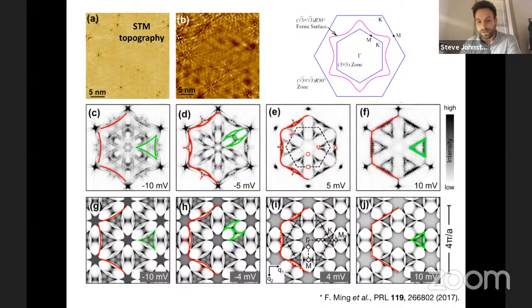And then you cross the Fermi energy at the unoccupied side, it pulls in even more. And when you go well above the Fermi energy, it almost flattens out and disperses even further in. So this is sort of the first empirical evidence we have that there is something dispersive happening in these peaks that are appearing in the power spectrum. And this is probably related to some sort of dispersion of the electronic states.